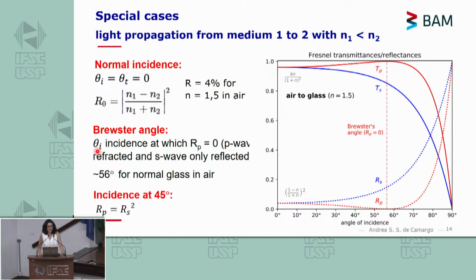There's another case, when the incidence angle θ is such that the RP component equals 0. So the P wave is refracted and the S wave is only reflected. And for a refractive index of 1.5, the Brewster angle is about 56 degrees. You can see it here, right? So you can see that RP, the reflection of P-polarized light, is 0, whereas RS is different than 0. So if you do incidence at the Brewster angle, you have an opportunity to select polarization, right? And this is very much used in optical components, of course. And then you have the correspondence here of TS and TP. And if you have incidence at 45 degrees, what happens is that the reflected P polarized component will equal the square of RS.